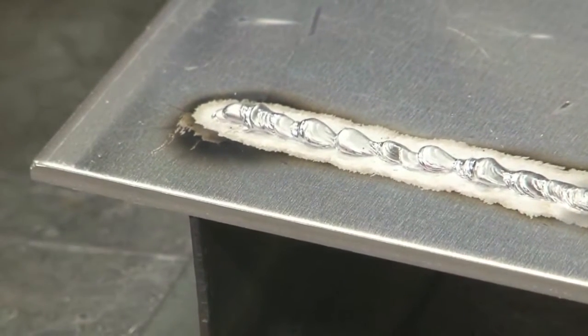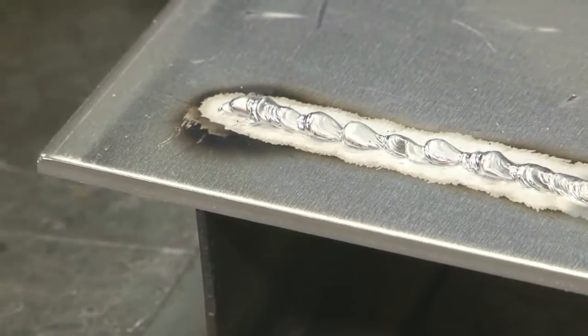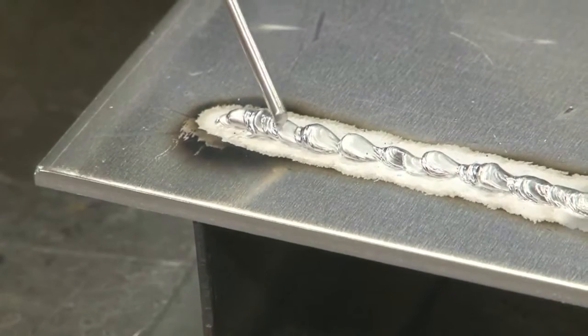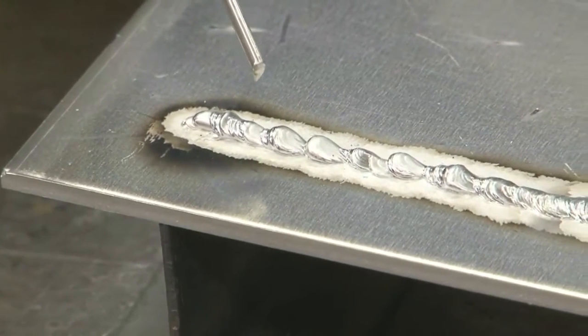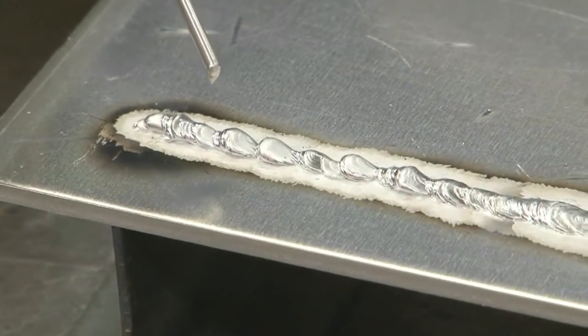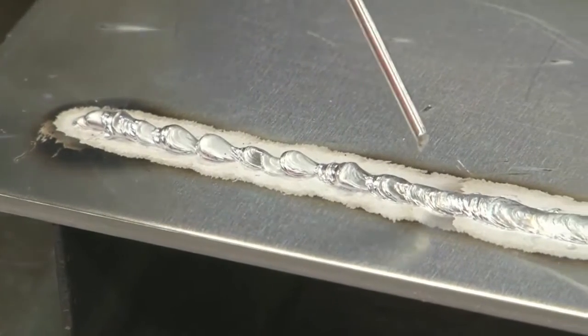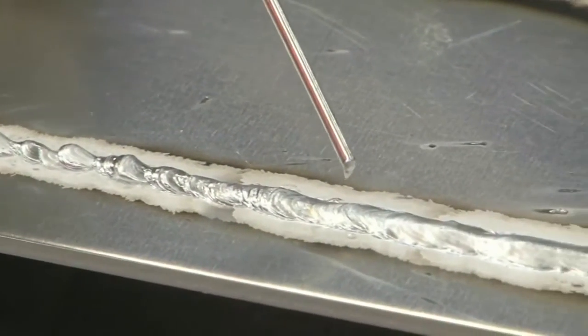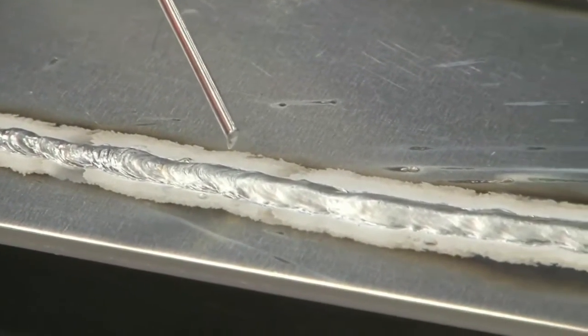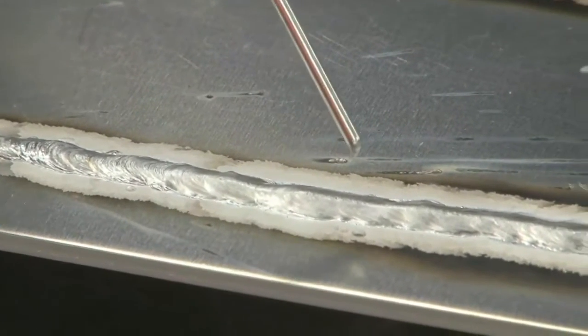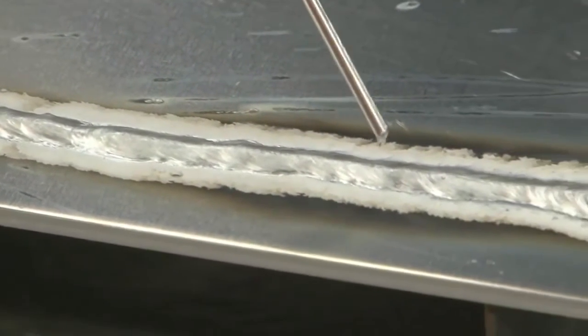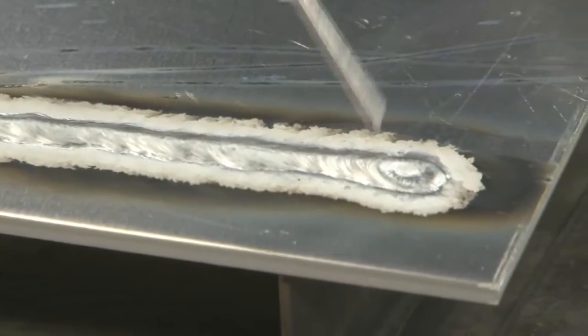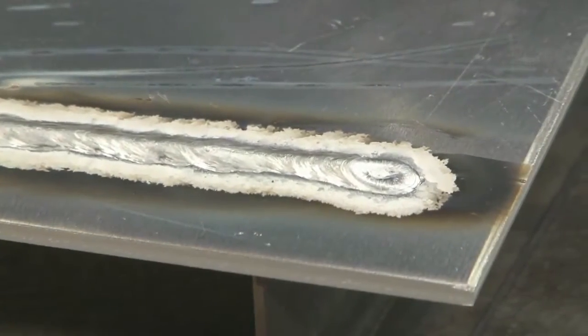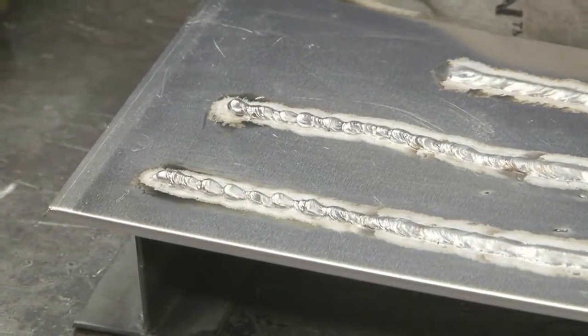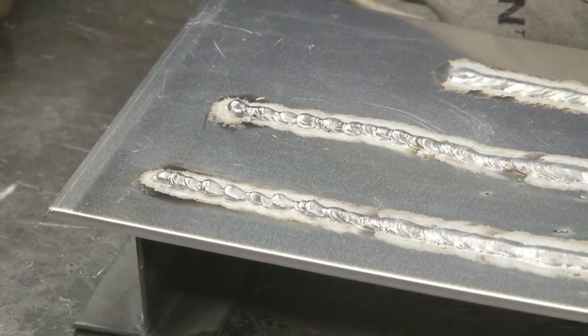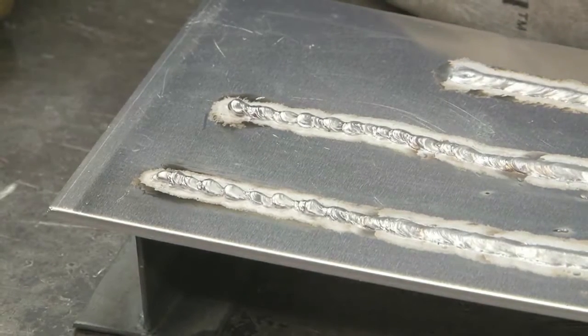So at the beginning of this weld, we were in the short-circuiting transfer mode. As you can tell, the bead is fairly convex, and we had a lot of spatter coming out of the weld pool. As we increased the volts, we got into a nice spray transfer mode, and the spatter disappeared. And then as volts continued to increase, we started to see the puddle getting a little bit on the hot side for 1/8" material.